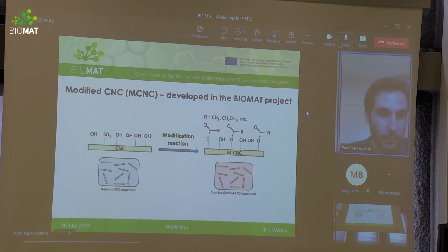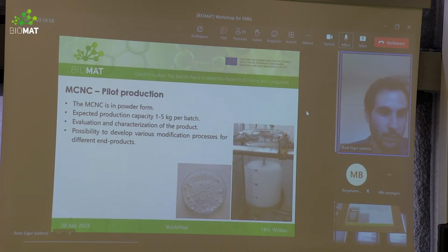As part of the BIOMAT project, Melodea developed and produced modified CNC. We developed a chemical reaction to change the surface of the crystals from hydrophilic to hydrophobic. We have reached pilot scale production of MCNC in powder form. The expected production capacity is 1 to 5 kilo per batch. We perform full evaluation of the product. We can develop different modifications for different products.